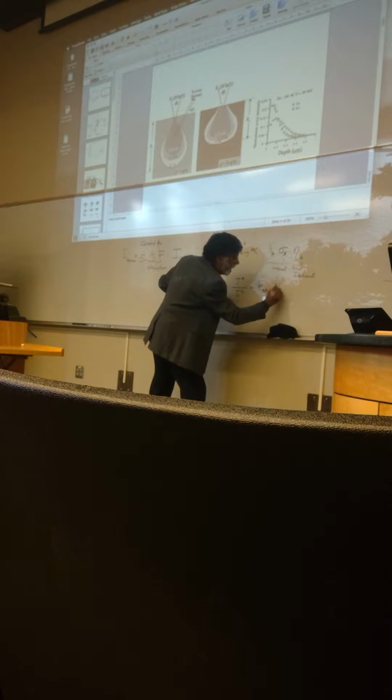And the way to do this, normally, the analysis is done by taking ratios. If you take ratios, you have the intensity of element A divided by the intensity of element B. You have a factor which is called KAB, times the concentration of A over the concentration of B. And this factor typically involves the cross-section and the efficiency.